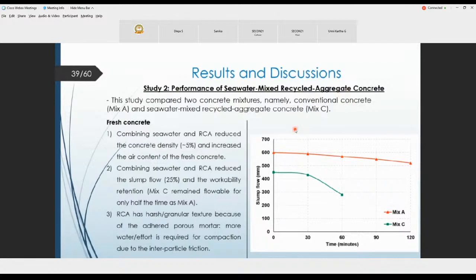This study compared again two concrete mixes: concrete mix A, considered a reference, where we use freshwater concrete and natural aggregate, with mix C, that uses seawater mixed recycled aggregate concrete.